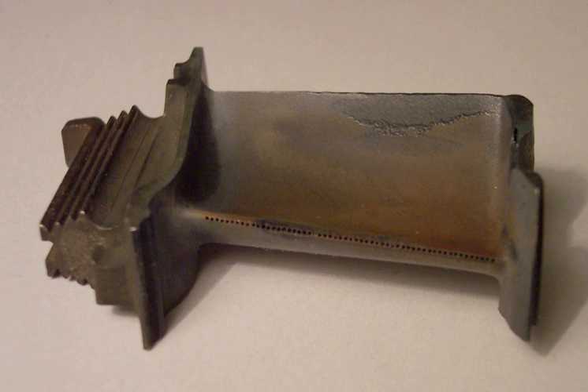Additionally, the volume fraction of the gamma precipitates increased to about 50 to 70% with the advent of single crystal or monocrystal solidification techniques, see Bridgman technique, for superalloys that enable grain boundaries to be entirely eliminated from a casting. Because the material contained no grain boundaries, carbides were unnecessary as grain boundary strengtheners and were thus eliminated. The second and third generation superalloys introduced about 3 and 6 weight% rhenium for increased temperature capability. Re is a slow diffuser and typically partitions to the gamma matrix, decreasing the rate of diffusion and thereby high temperature creep and improving high temperature performance and increasing surface temperatures by 30 degrees Celsius and 60 degrees Celsius in second and third generation superalloys, respectively.